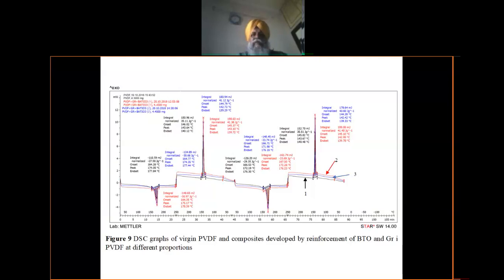And we can see some of the optimization parameters. Here you can see this is again a thermal analysis of this type of material. You can see the effect on PVDF, then PVDF, graphene, and BaTiO3, with different proportions. So, whether my material is thermally stable, basically we get three basic pieces of information out of this type of thermal testing. One is the glass transition temperature of the material. Glass transition temperature means that after that temperature, the material is going to have a plastic behavior, and before that temperature, it is going to have a glassy behavior, right?